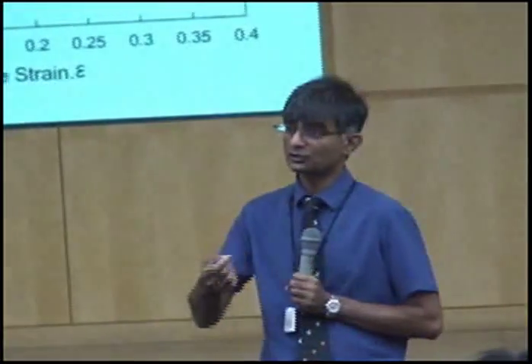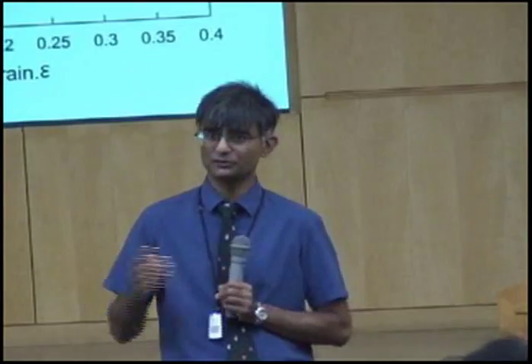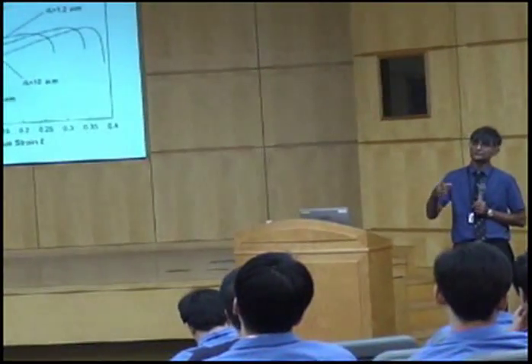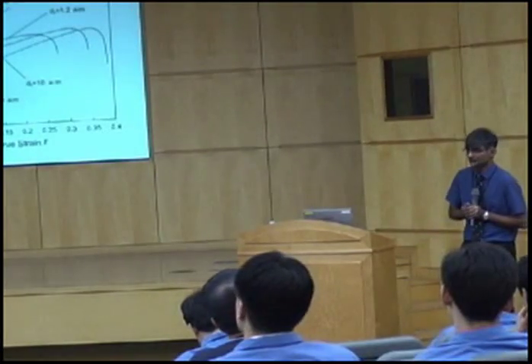Okay? So all the work that has been done in producing very fine grain size, either by severe deformation or by very rapid cooling, etc., has failed. You do not get ductile materials. Okay? I don't know of a single example where a very fine grain structure, the so-called nanostructures, have produced ductile material. Okay? And that is simply because you lose the capacity for work hardening. And I'm going to show you how to recover that capacity for work hardening and actually produce a nanostructured steel later on. So going to a fine grain structure is not always a good thing. You have to not just increase the strength, you must also improve the other properties of the material.